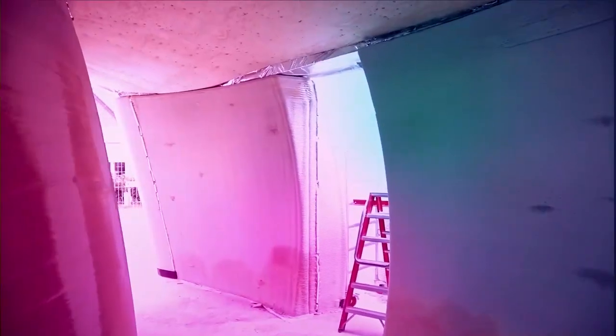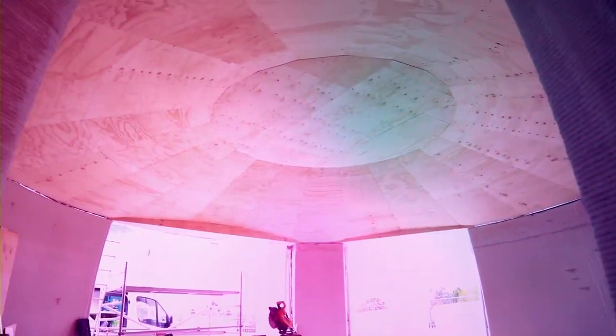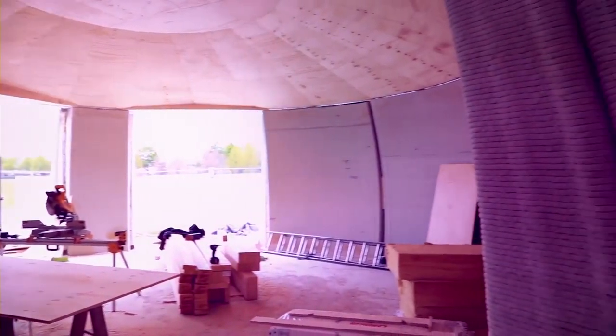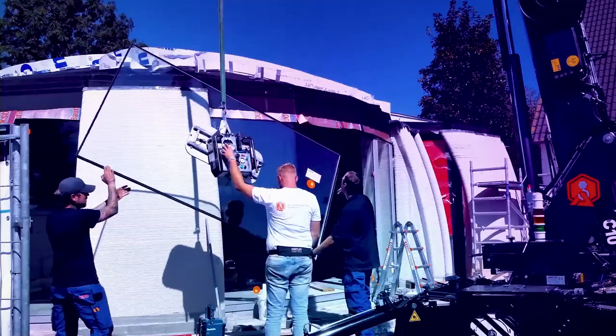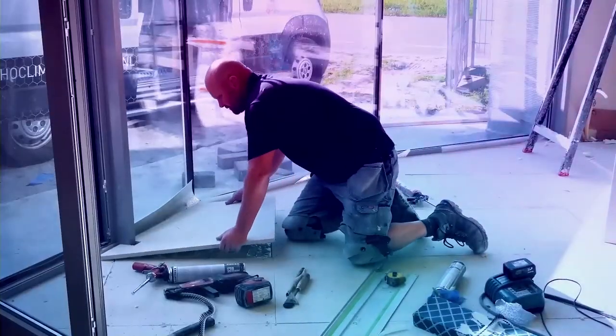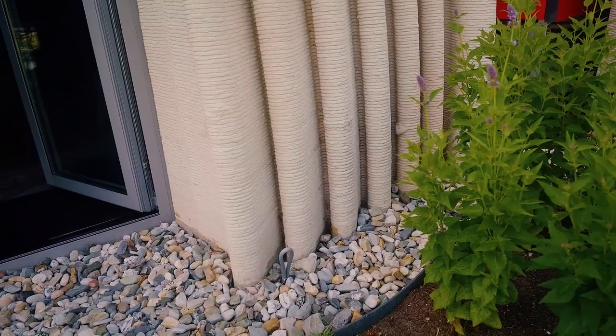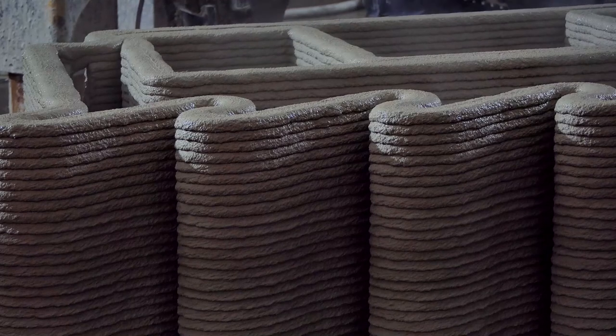One of the things we've learned in this project is that the 3D printed mortar, which we have used for this project, reacts with the cast in situ concrete, which created a dark brown finish on the outside of the printed walls, which was not intended in the design. Another thing we learned was that it's difficult to print with a fast hardening mortar outside, which created cracks during printing in some of the wall elements, which then had to be redone.